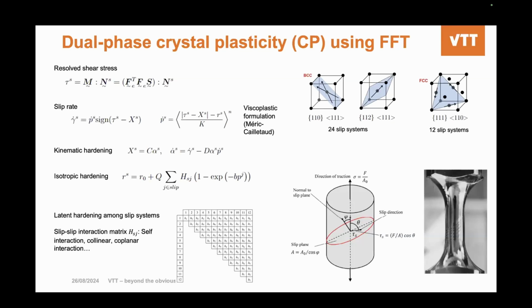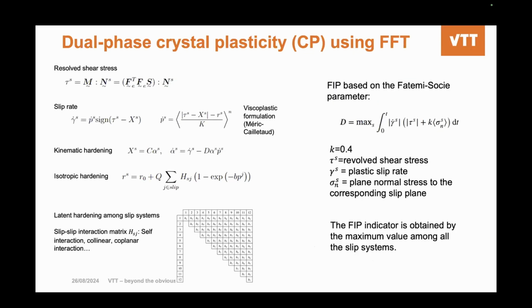Here's a brief introduction about the crystal plasticity model I used. It's nothing special. It's a Méric-Cailletaud type crystal plasticity model. We have the slip rate, the kinematic hardening, and isotropic hardening. We have interaction matrices between different slip systems from the literature. For the BCC martensitic phase, we have 24 active slip systems, and for the FCC phase, we have 12 slip systems. To study the fatigue property, we have used a Fatemi-Socie-like fatigue indicator parameter. As you know, fatigue is governed by both shear components and plane normal components. So, okay, I will go quickly.